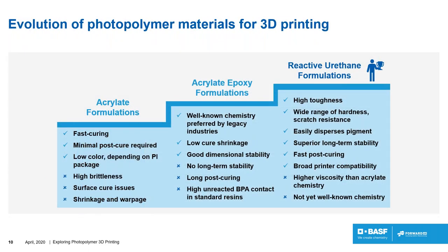Let's now come back to the core of the solution: the materials. Material chemistry has evolved and improved over the last 30 years. Everything started with 100% acrylate formulations, which were very fast-curing, required minimal post-curing, and could produce very transparent parts. However, they were brittle, caused surface curing inhibition, and had significant shrinkage and warping — acrylate really shrinks and curls a lot, causing major deformation.